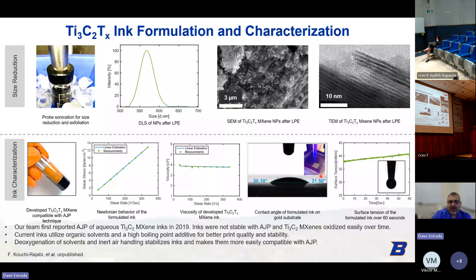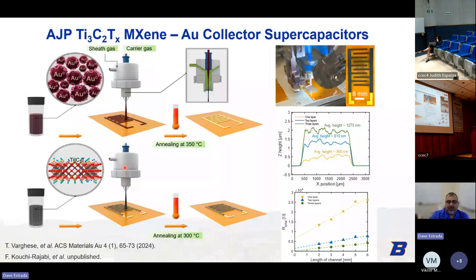So to make the supercapacitors, we actually start by printing our current collectors, for which we're using our in-house generated gold ink. So we use the aerosol jet printer to print the current collectors in an IDE structure. We anneal that at 350 to remove solvents and the PVP. And this is done on polyimide. And then we come over with the aerosol jet printer, retrace the IDE structure, and deposit the MXene layers.